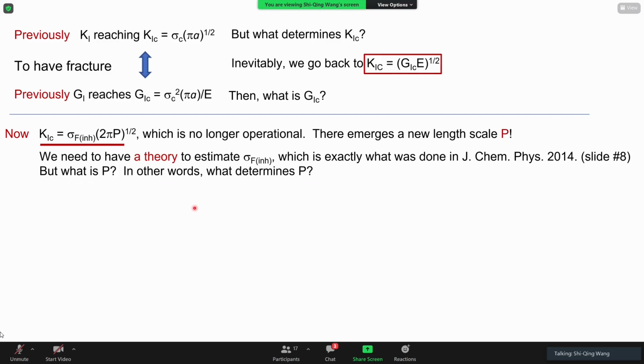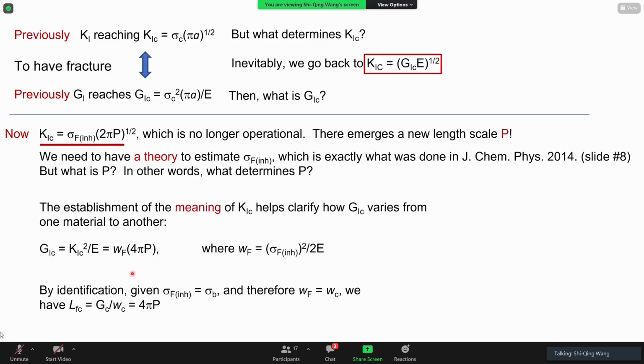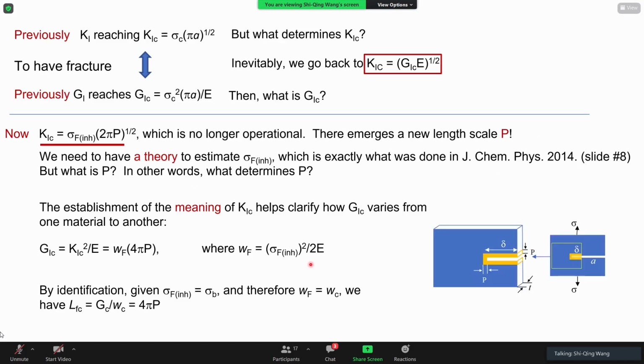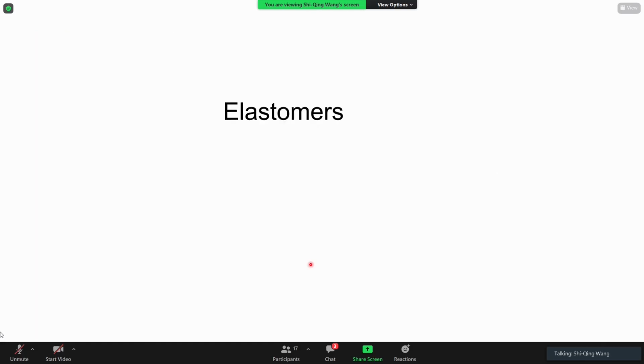In any case, this actually tells us that we should concentrate on finding out what is the inherent strength of our polymers, which is what we have done. So this is why we are entering fracture mechanics, because we have some insight about what determines the inherent strength. More interestingly, since they are related, you can even have an expression for Gc and ask what Gc is determined by. Well, it's determined by the same characteristic length, and it's determined by the energy associated with this inherent strength. Okay. And you can assign some specific intuition to what this P is. So let me just use my next 5 minutes to talk about elastomers.